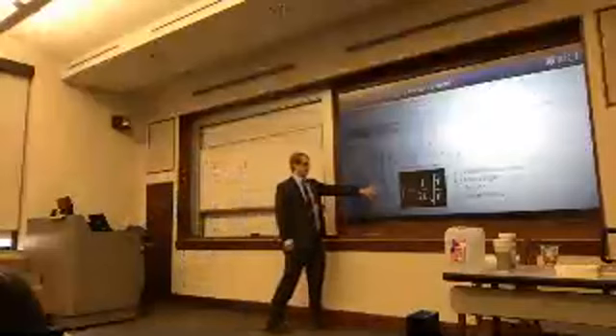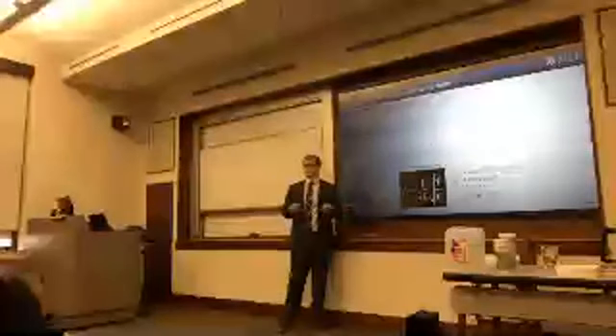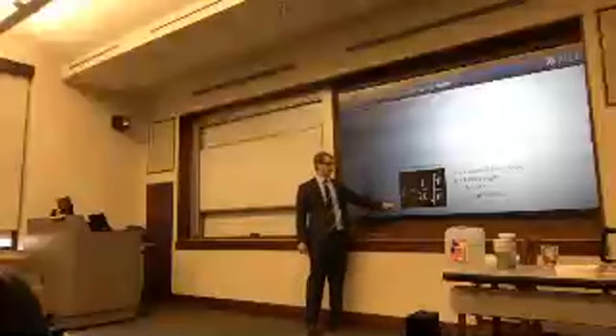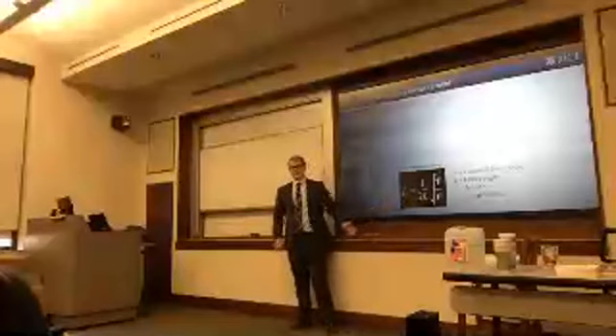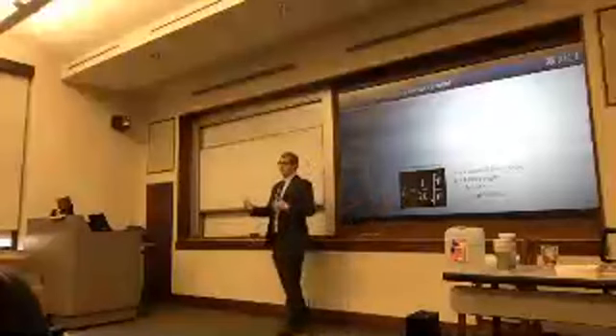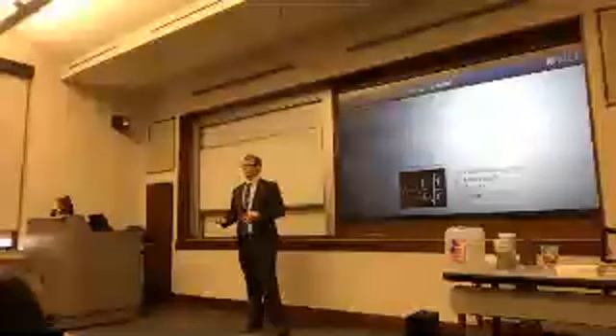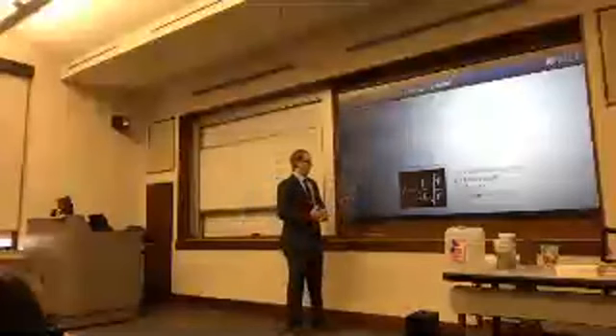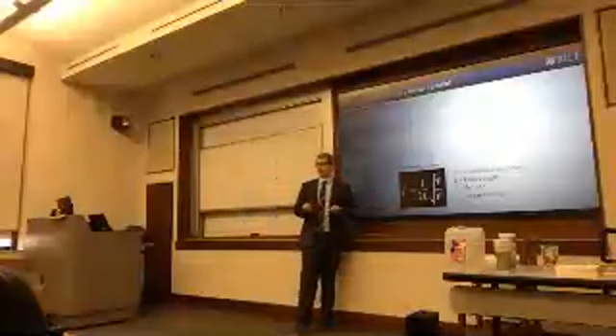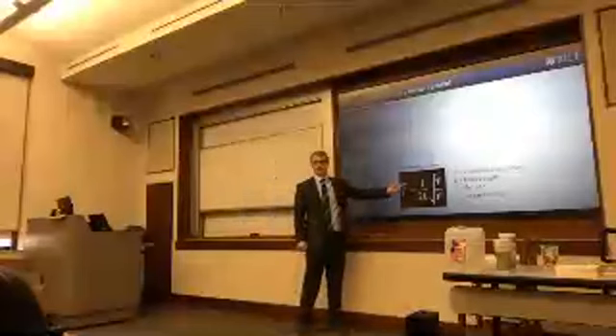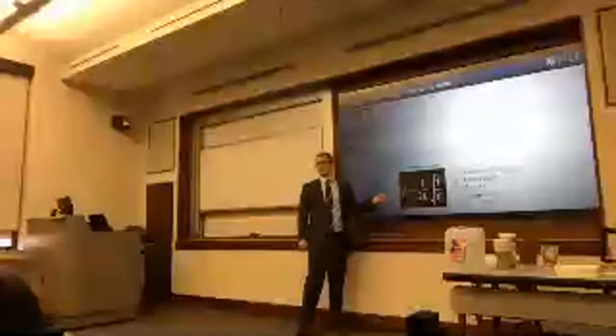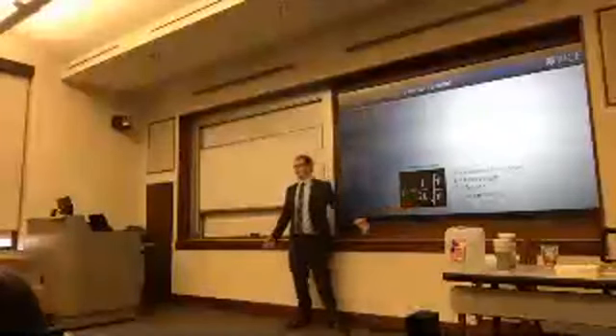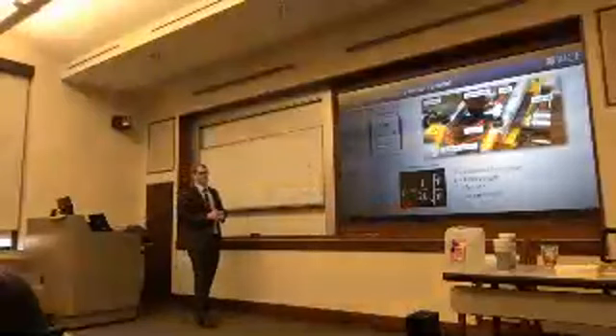And the method that we have developed comes from Mersenne's laws, which says that the resonant vibrational frequency of a suspended filament depends on its length, the tension that it's under, and its linear density. So this is essentially the equation that governs the sound that's produced by a vibrating guitar string. So with a carbon nanotube fiber, if we take a suspended carbon nanotube fiber and we know the length, and we measure the tension on it, and we cause it to vibrate at a known frequency, then we can back calculate the linear density.